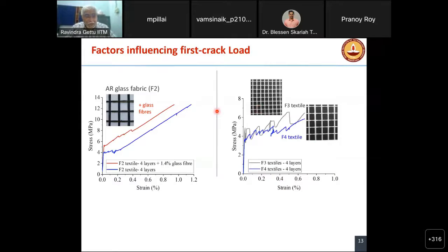Also, we can see how to increase the initial cracking. The first crack depends on the matrix. But what we found is that if we add glass fibers or we have close knitted textile, then the first crack goes up. Otherwise, it's mostly the binder behavior, the matrix behavior. But what we have seen is that if we add a few glass fibers or we make the textile architecture slightly different, then the initial load carrying capacity increases. So that means the first crack is delayed or it occurs at a higher load. So we can influence also the first crack by this type of behavior.